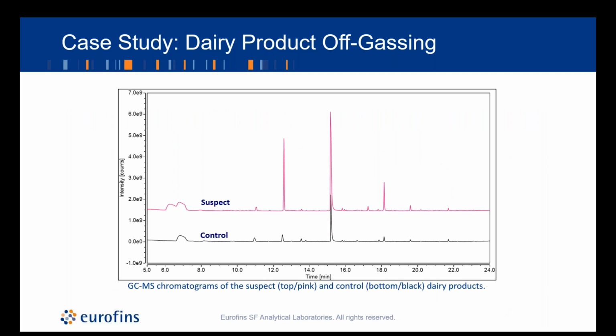So you'll notice right away we have the same major peaks between these two samples, our suspect and control, but the intensities are very different. These peaks here were identified as ethanol, acetoin, acetic acid, and 2,3-butanediol, and they are all elevated in our suspect sample.